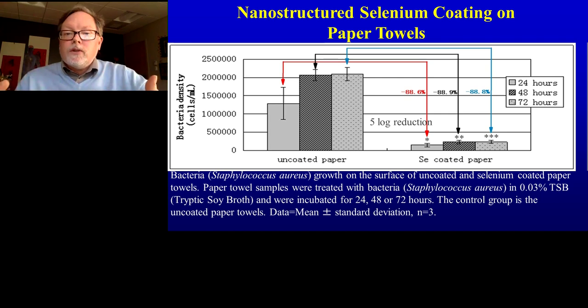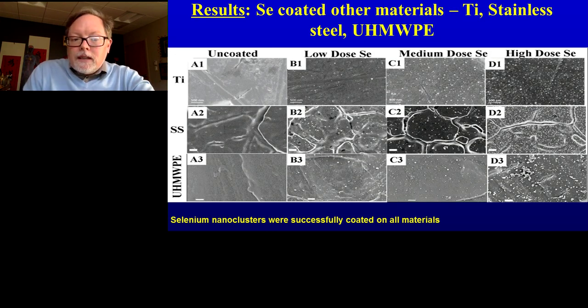So what we propose to do is to treat paper towels with selenium, nanoparticles of selenium, to really keep bacteria from growing on these paper towels or on other materials that might be in the hospital or everyday life setting. We've also been able to coat metals, stainless steel, ultra-high molecular weight polyethylene.